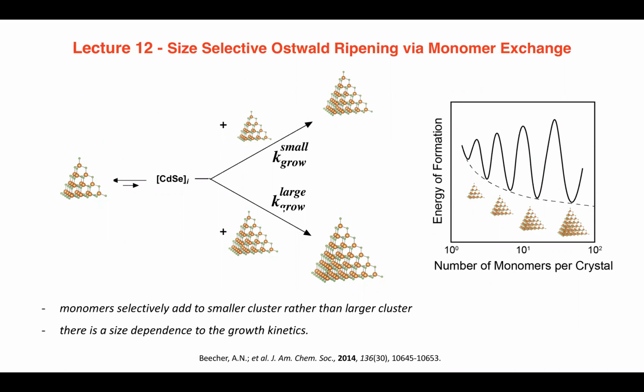So you start off down here, and the thing is getting to lower and lower energy, but it's harder and harder to get there with time. The fact that the barrier goes up while the reaction becomes more driven is very unusual. Generally speaking, when a reaction has a very large driving force, it's thought the rate will be faster. But the inverse is happening here.